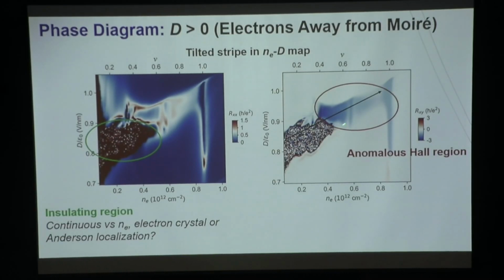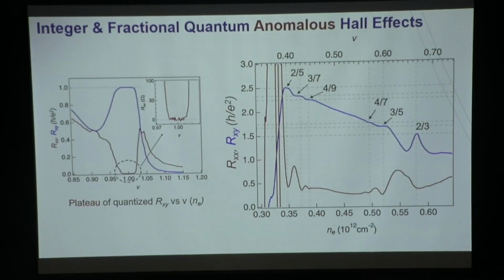This is taken at zero magnetic field. Not only having anomalous Hall, but there are structures on the map. There is a stripe at filling factor 1, which means 1 electron per Moiré superlattice unit cell. And there are features at the fractional fillings of Moiré, right? 2/3, 3/5, 2/5. And you can tell these features from both the Hall resistance and the longitudinal resistance maps. So all these tell us that we are probably getting a topological flat band. So the flat band effect breaks the degeneracy between K and K prime, so I get the net anomalous Hall signal. Okay? And taking a closer look, this is at the integer filling, 1 electron per Moiré.